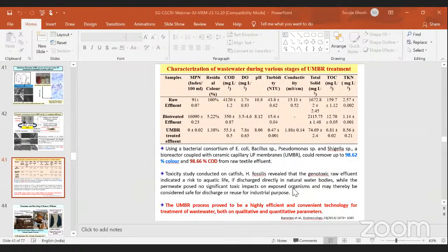This is the characterization of the wastewater before and after UMBR treatment, that is ultrafiltration induced membrane bioreactor treatment. And this process was found effective for a combination of bacteria like E. coli, Bacillus species, Pseudomonas species, and Shigella species. When this consortium of bacteria was applied, coupled with the ceramic ultrafiltration membrane process, it worked best, and about 98.6% removal of color and 98.66% removal of COD was achieved from the raw textile effluent. And also the effluent was free from toxic impact.